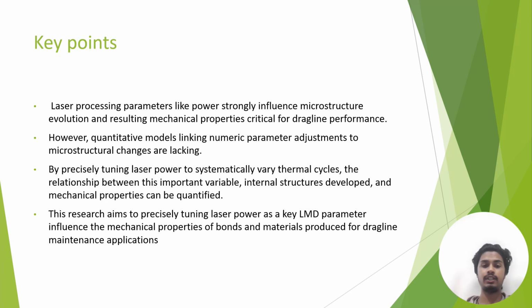Therefore, by precisely tuning the laser power to systematically vary the thermal cycles, the relationship is important, since the internal structure developed and mechanical properties can be quantified from this. Therefore, this research aimed to precisely tune laser power as a key LMD parameter influencing the mechanical properties of bonds and materials produced for dragline maintenance application.